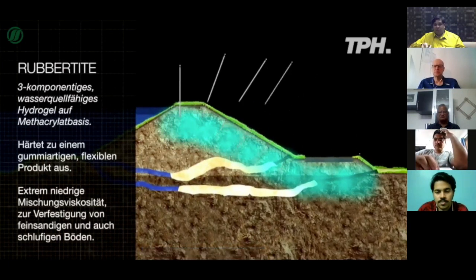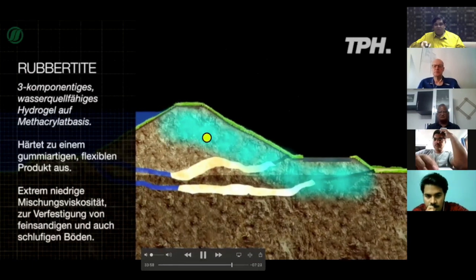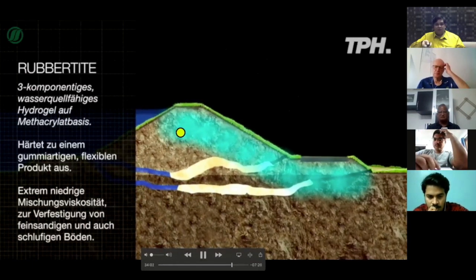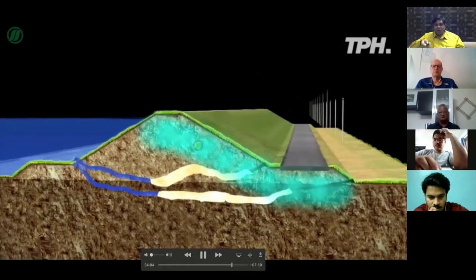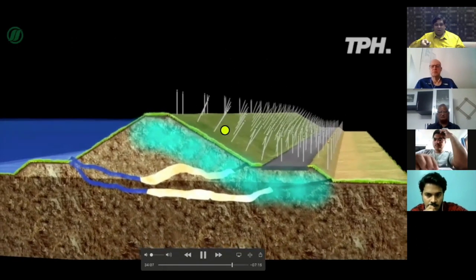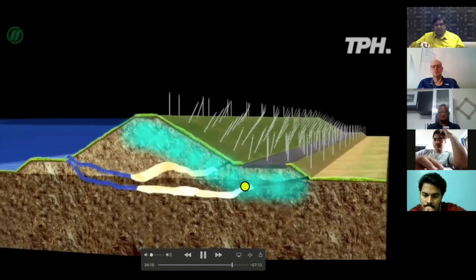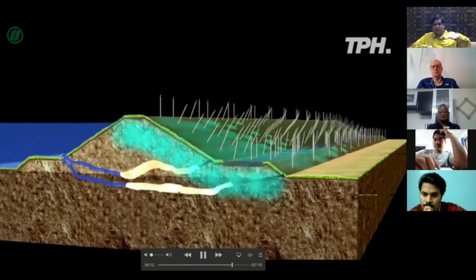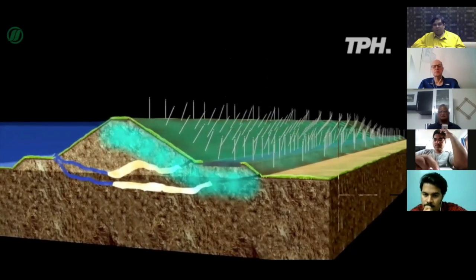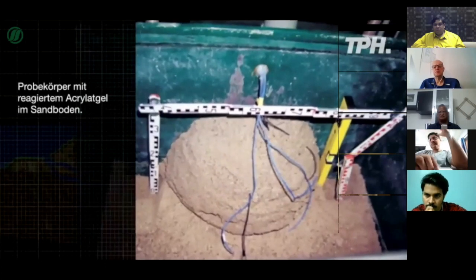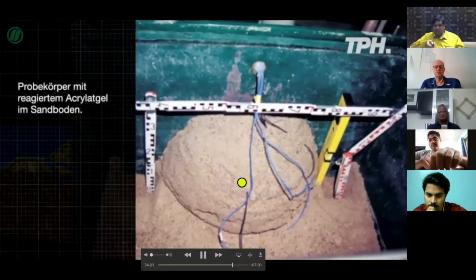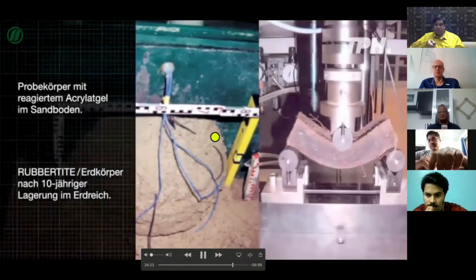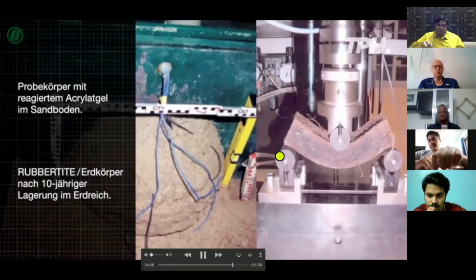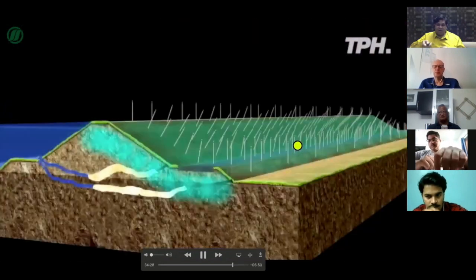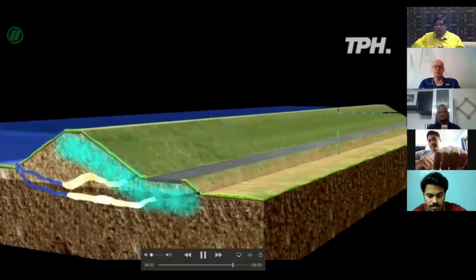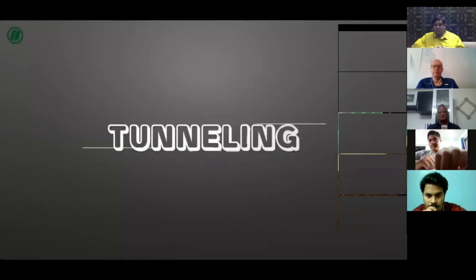And then on top of that, you can stabilize it with something like a methacrylate based system, Rubbertite. You do this again in a grid across the entire dike, and after that this entire area can very easily take the loads. There is no further ingress of water. In the picture here, you can see how effective it is at consolidating those kind of strata. This was tested in practice for over 10 years. You can see the ductility of that kind of material, so it can very easily be done.